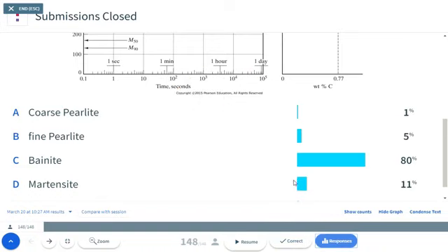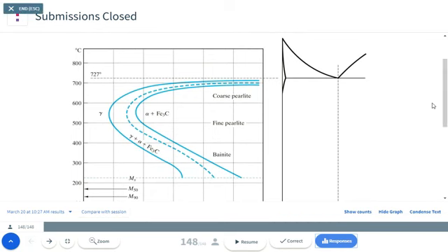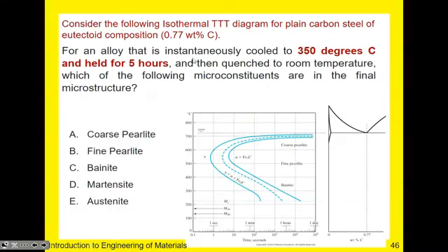Okay. Well, yes. An overwhelming majority of you said 80% bainite. So it is exactly what you're thinking, which is if you have 0.77 weight percent carbon, this is your phase diagram. Your composition does not change. This is the chemistry that you have. Then you drop the temperature very quickly to 350, which is about here. And because it's instantaneous and it's isothermal, you can assume that you've beat the nose. That means you haven't gone into this territory yet. And so if it's all the way down to 350 and you wait 5 hours, that gets you to here-ish. Actually, it gets you to 1, 2, 3, 4, 5. So it gets you to about here. That means you've gone through 1% transformation, 50% transformation, and now 100% transformation. You're well beyond 100% transformation to bainite.